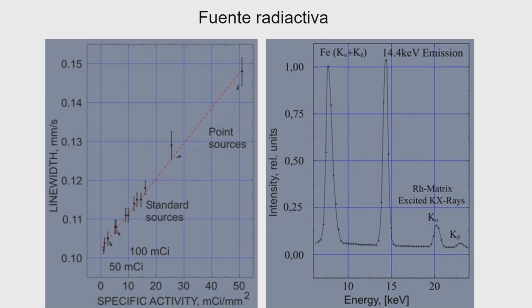Okay. And usually, what you see if you obtain a gamma ray spectrum from your source, then you see several lines, but you're interested in this line. This line is the one originated in the photons of 14.4 keV. So you have to have a means to get rid of the gamma rays which don't belong to this particular line.